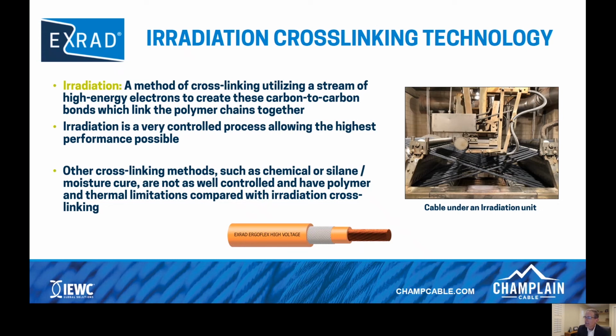And the image on the right is cable underneath an irradiation unit. You can see it is set up in a figure-8 configuration, and it runs around and around and gets bombarded by high-energy electrons during the process, and that causes the hydrogens to break away from the carbon and causes the carbon to attach to another carbon and form the cross-linked final product. Now, of course, in wire and cable, there are other cross-linking methods, such as chemical or silane moisture cure cross-linking. Those methods are not as well controlled, and they also have polymer limitations and thermal limitations compared with irradiation cross-linking methods.